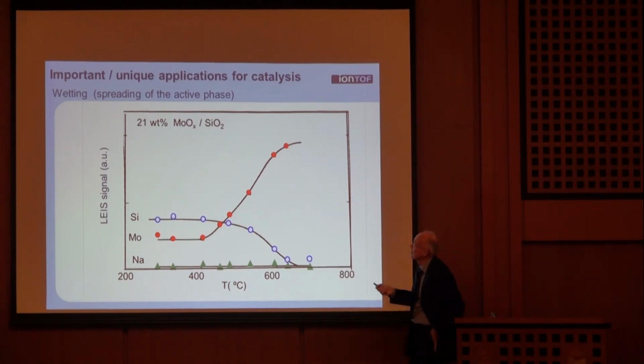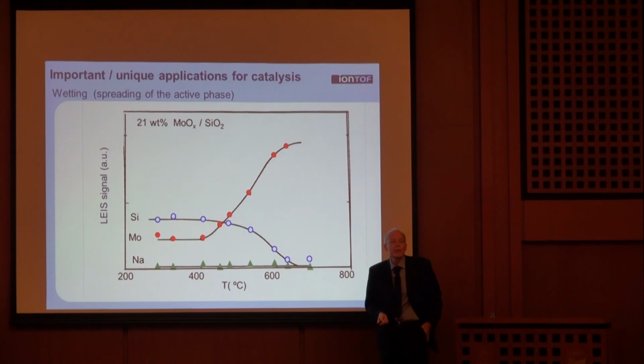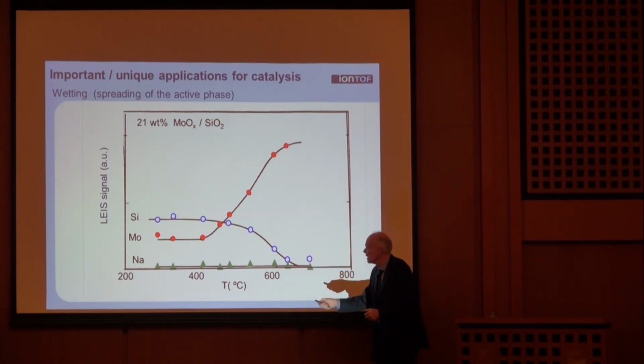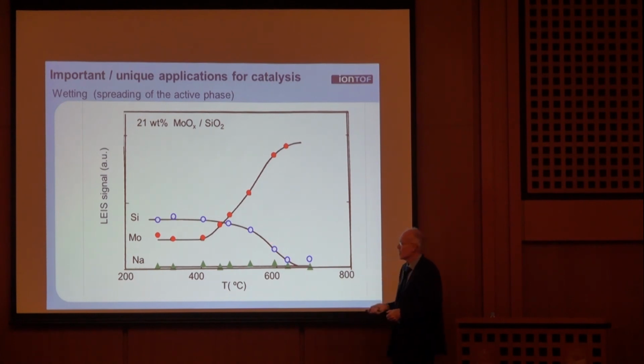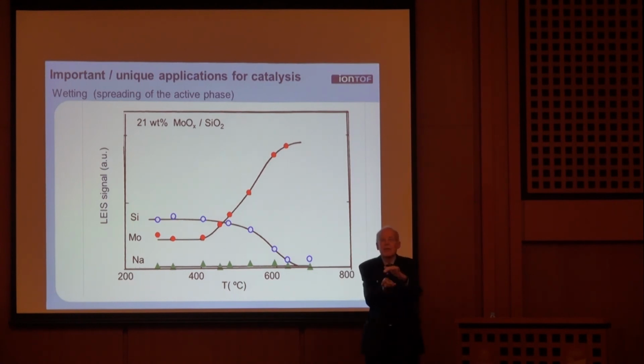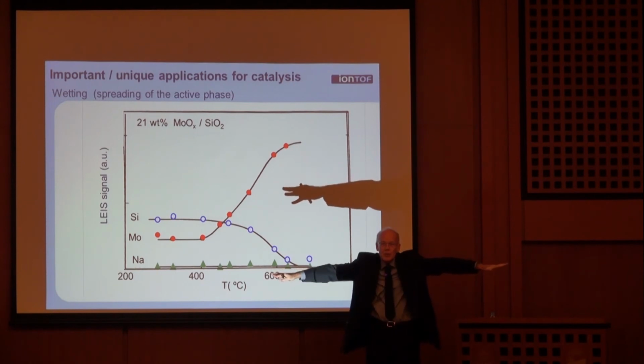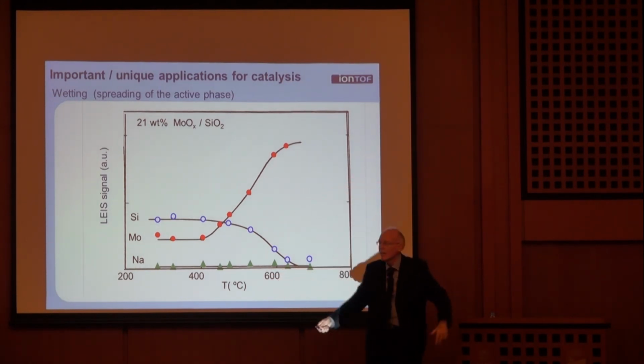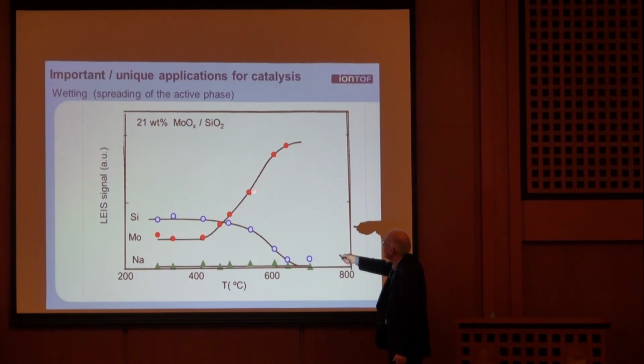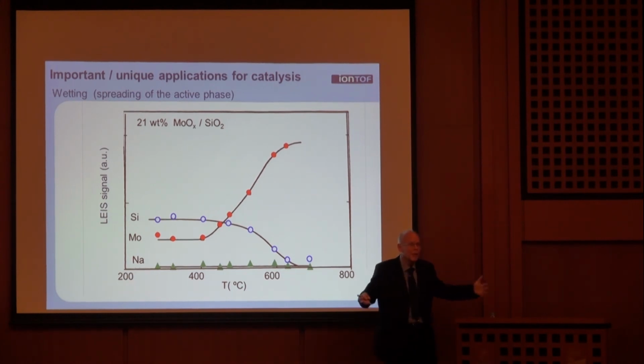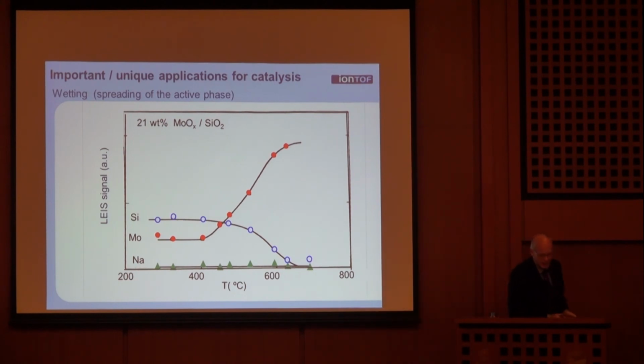One of the applications is wetting or spreading of an active phase on a catalyst. So this is a case where there is molybdenum oxide on top of a rough silica surface, and by heating you see that the silicon signal goes down, it disappears completely, and the molybdenum goes up. What happens? Well, you start off with clusters of molybdenum oxide, and they just spread on the surface. They wet the surface. And so in a quantitative way, you see here, at the end, it's fully covered by molybdenum oxide, and there's no silica anymore. So wetting or de-wetting, that kind of processes are easy to follow.